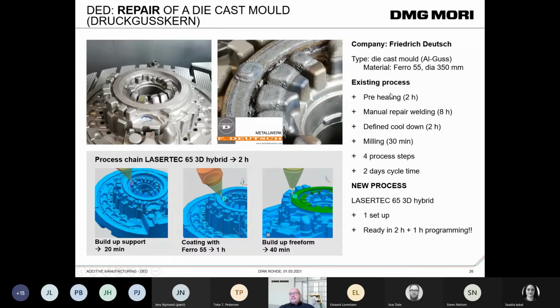So the existing process is the preheating for the manual repair welding. Then you have the cool down, the milling again, and a total loss of 2 days to repair this core. On our machine, you have only one setup. You put the core into the machine, machine it off, weld it, have a few minutes cool down, and then finish it in the milling process. Why is it not necessary to preheat this part? The heat impact of the laser is such a small dot that the heat impact of the overall part is very, very little. So you typically do not have too much stress compared to manual repair welding, which is also very rough. You weld big areas and you lose many details, and everything has to be machined off again.